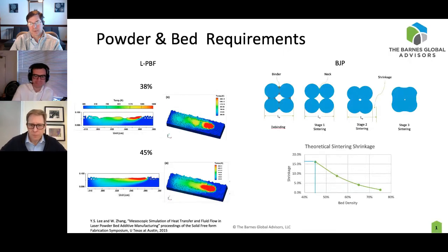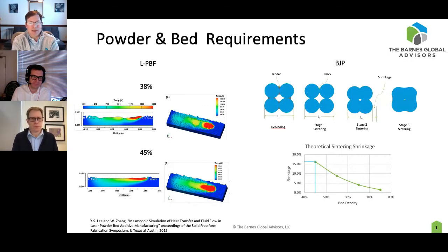That's right. My perspective is if we're comparing binder jet to traditional press and sinter, in traditional press and sinter the range of particle sizes is 1 or 5 to 150 microns. The resultant porosity is also very different than if we're using a pure metal binder jet with a D50 or a D90 of minus 22 microns, right? The largest pore size is going to be in the range of the largest particle. And so comparing a structure with many 150, 200 micron pores looks very different than a structure with a number of 10, 25 micron pores.